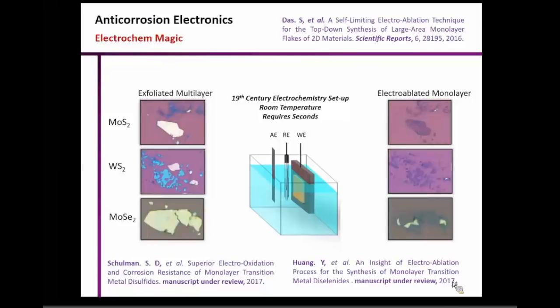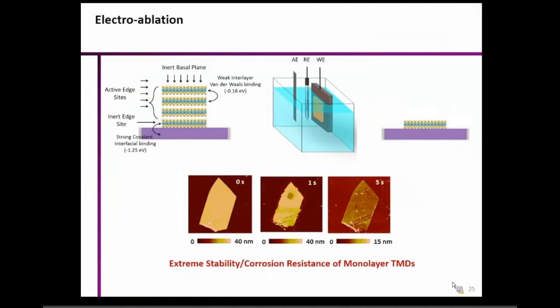And that actually happens for pretty much most of the 2D material. You start with a multi-layer flake, you just do this corrosive process, and the monolayer survives, while the bulk material actually disappears, which shows the strength of this monolayer in this corrosive environment. Now let me explain a little bit about what's really going on. Why do we have this monolayer surviving in the corrosive environment while the bulk layer is gone?